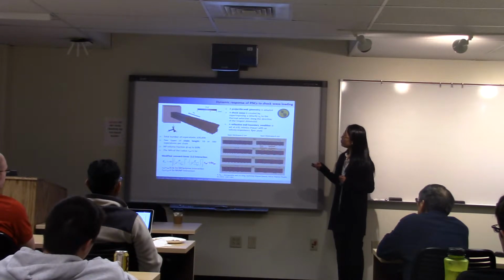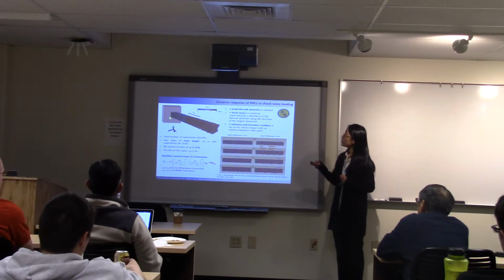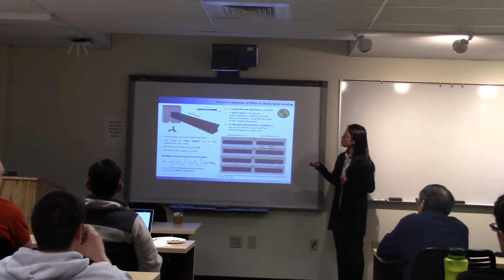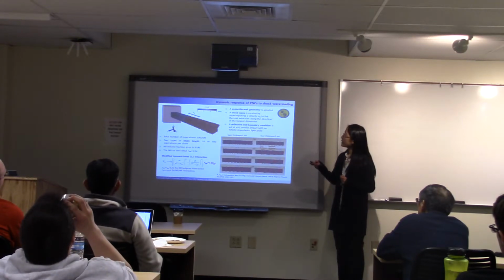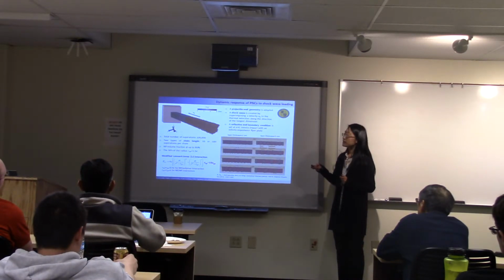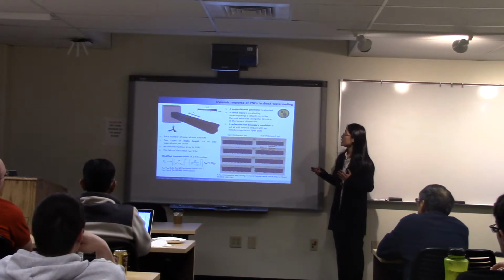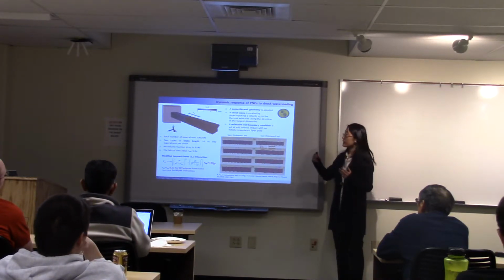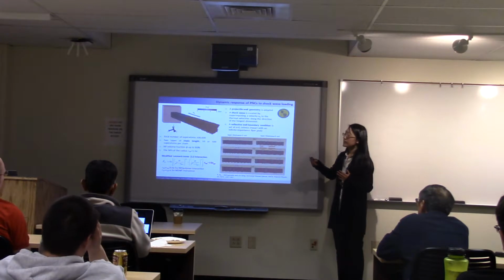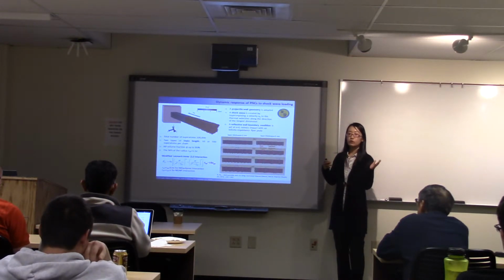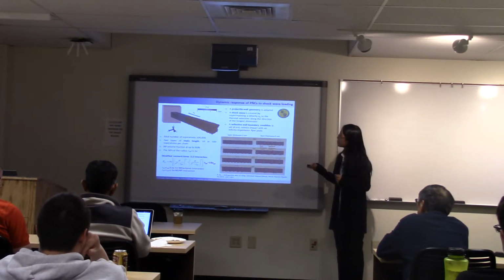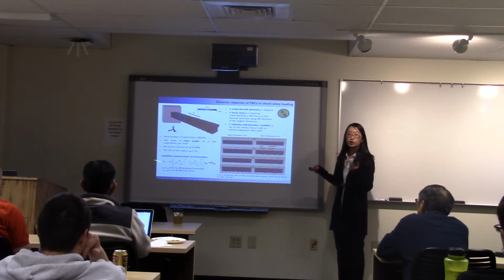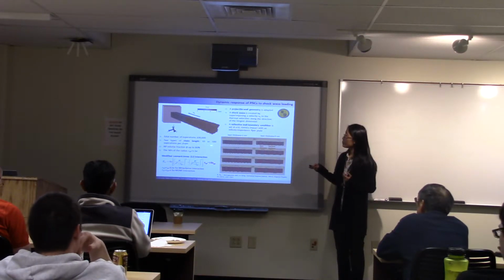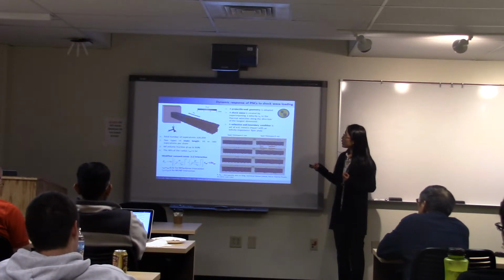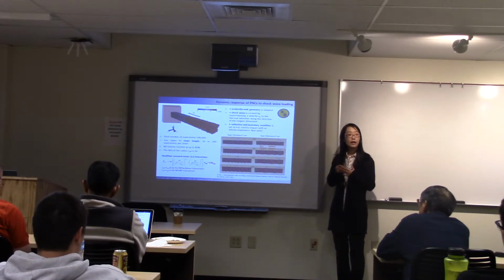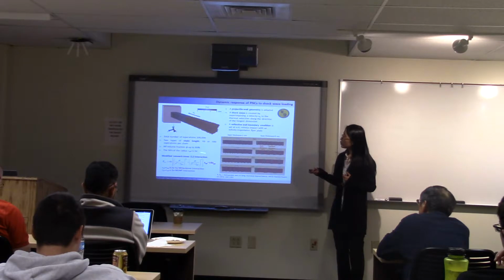To initiate the shock wave, we used this projectile-wall geometry, just placing a wall at x equal to 0, having a reflective wall boundary condition. So when this polymer bar is given a velocity and hits this wall, you will get a reversal of the velocity. We consider two cases of the chain length, 10 and 500. We also consider uniform nanoparticle loading up to 31%.